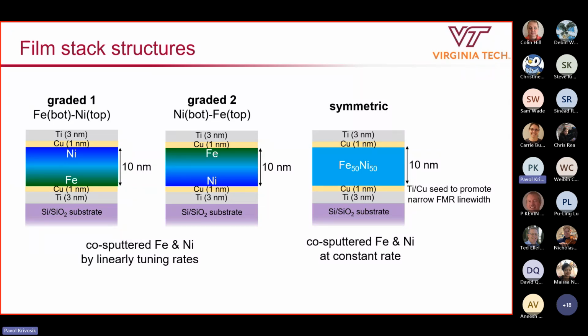Now, of course, we also have to cap each one of these films with something to prevent oxidation. And we also went with copper titanium there in order to preserve the overall symmetry. So this is to say that, in this sample series, the only source of symmetry breaking is presumably our compositional gradient here. Right, so otherwise everything else is symmetric. As symmetric as we could make it, at least.